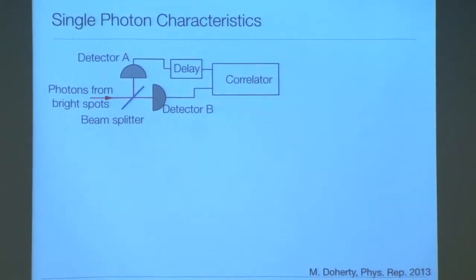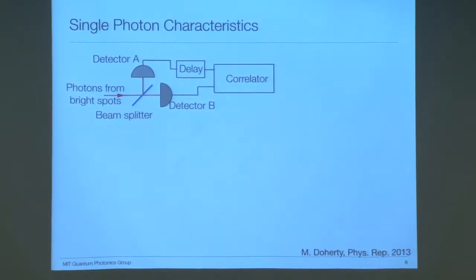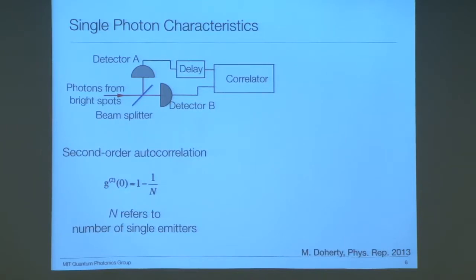By splitting the photons from this bright spot onto a 50-50 beam splitter and detecting them with 2 detectors, we record the correlation histogram of detected photons. The expected value of the second-order correlation function at 0 is given by 1 minus 1 over n, where n refers to the number of single emitters. With a single emitter, the g2(0) value will be 0, and with 2 emitters, this value will be 0.5.